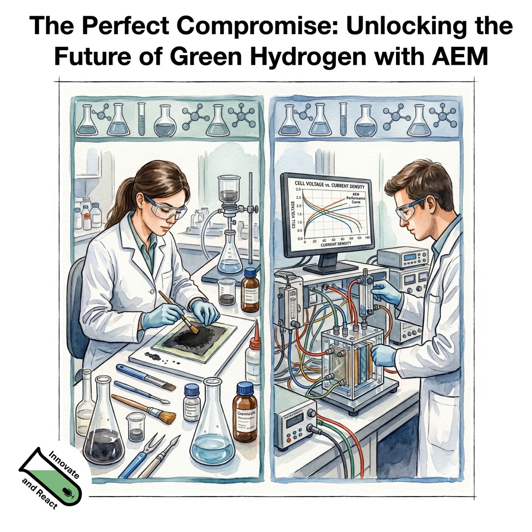And you mentioned also that you used to combine nickel with other elements to, in the end, use less of the active material, right? Or why do you combine the nickel? Yeah, so nickel is active, but nickel can be more active in combination with, for example, sulfur. And sulfur is interesting because in our projects, together with AEM, for example, in Schwäbisch Gmünd, we had a project where we did a nickel-sulfur catalyst layer by electrodeposition. And this was interesting because we found out that nickel-sulfur can influence the electronic structure, for example, and the conductivity.